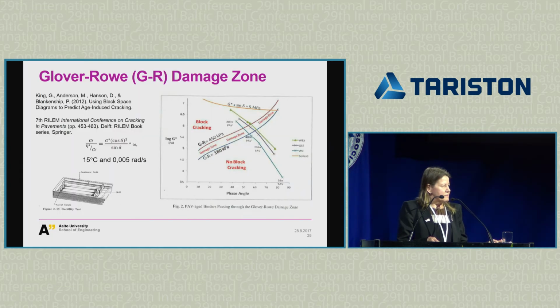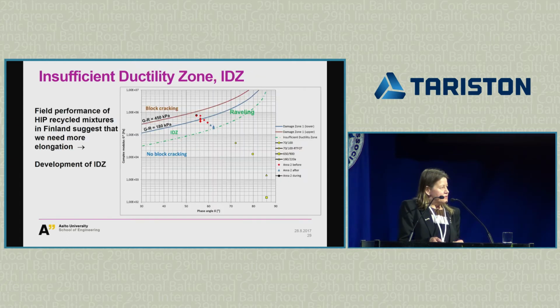So performance parameters. We found this parameter from the literature, which relates G-star measurements to the elongation of bitumen in a certain temperature and loading range, and the damage zone that these researchers came up with. They concluded that there is a bad area, block cracking, and then a good area on the other side, where you can be and where you shouldn't be. And we took this idea and tried it in our test roads in this very big research we did, and plotted the samples we had.